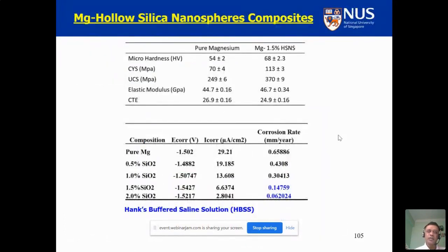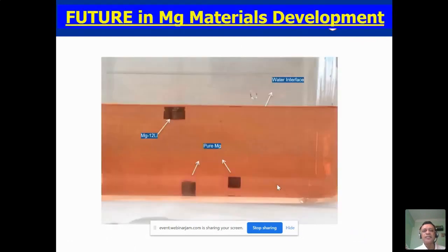We also tried the hollow silica nanosphere, and again you can see the increase in the strength and also the increase in the hardness. And if you look at the corrosion rate, it is very low. So that means not only the ones I've shown you, you can also use a silica nanosphere as a nanocomposite for biomedical application.